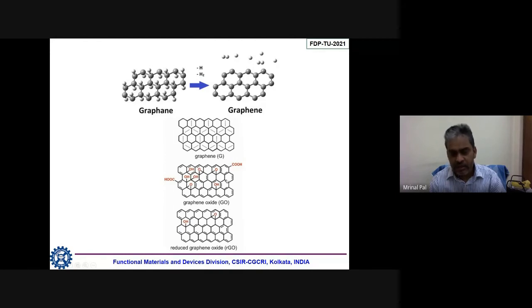So in general, it says that it is graphene with a lot of oxide groups, though there are some other groups, but it is graphene with a lot of oxide groups. That's why this is called graphene oxide. And from that, if you reduce using some kind of hydrazine or sodium borohydride, then you will get reduced graphene oxide. We call it RGO. This is the structure of this reduced graphene oxide. In this case, almost all the oxides are gone, but some functional groups like oxygen or OH may remain there.